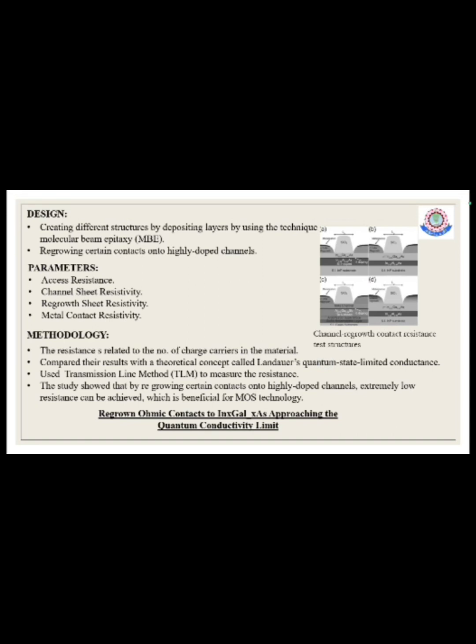In this experiment, they created different structures by depositing different layers of specific material using the MBE, molecular beam epitaxy method. They made 4 different samples for the channel material. They are 25 nanometer of indium gallium arsenic, followed by 100 nanometer of heavily doped indium gallium arsenic, and then 100 nanometer of heavily doped indium arsenic, and finally 15 nanometer of indium arsenic.